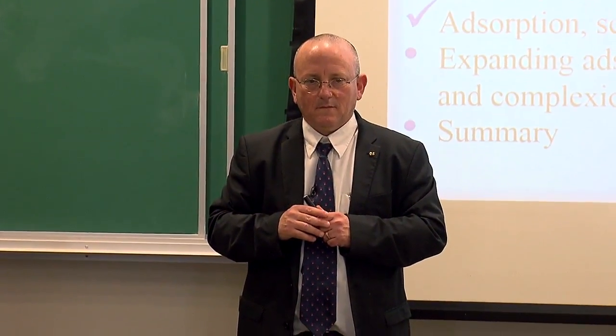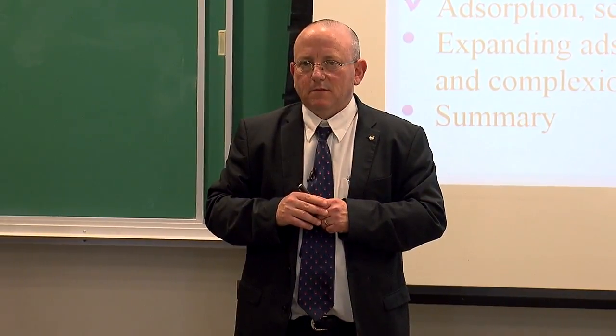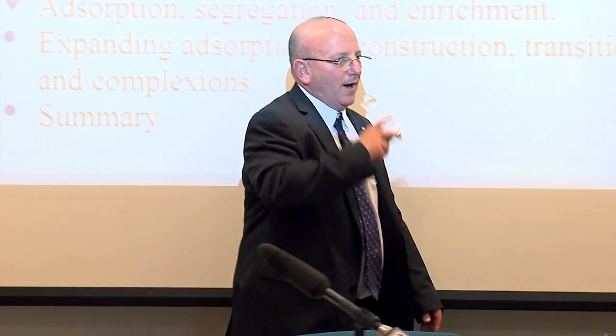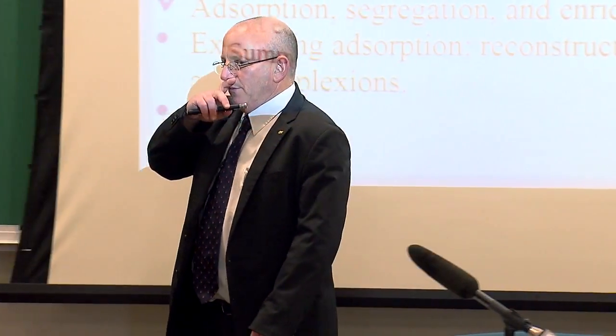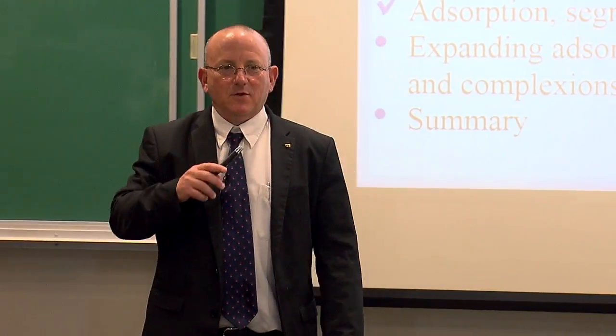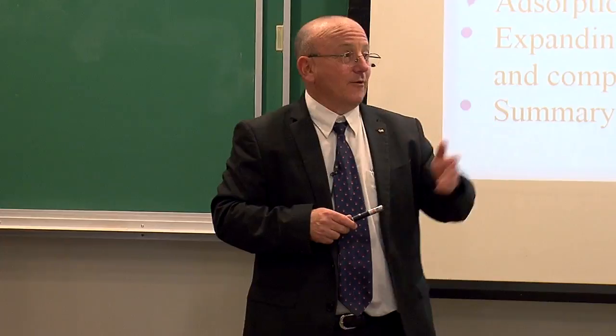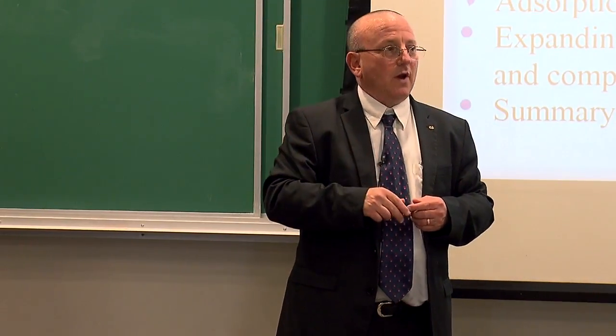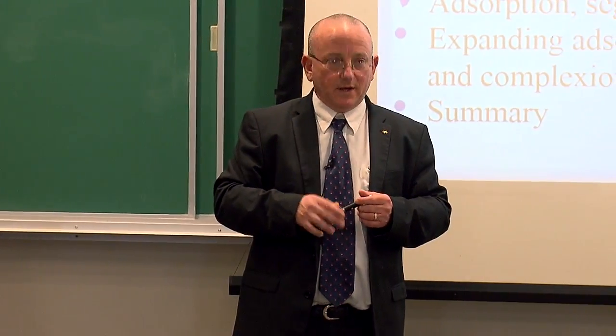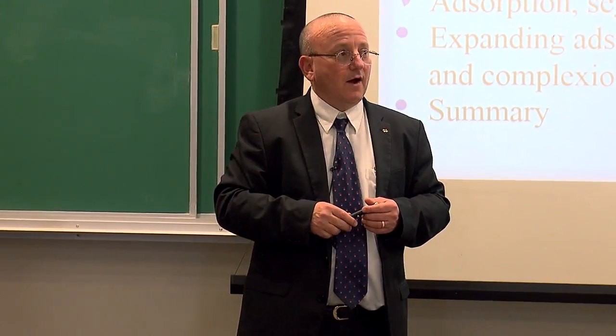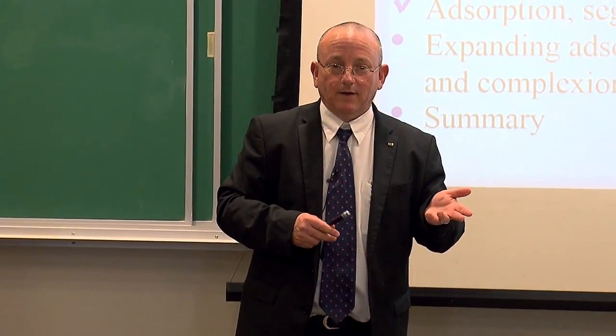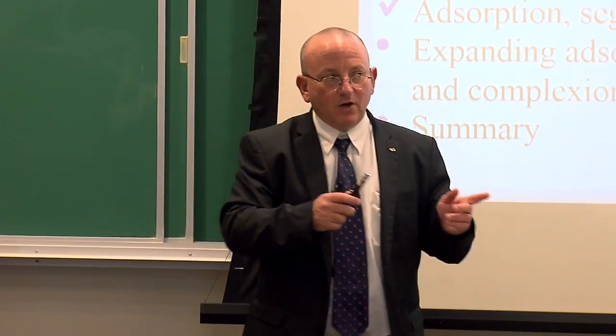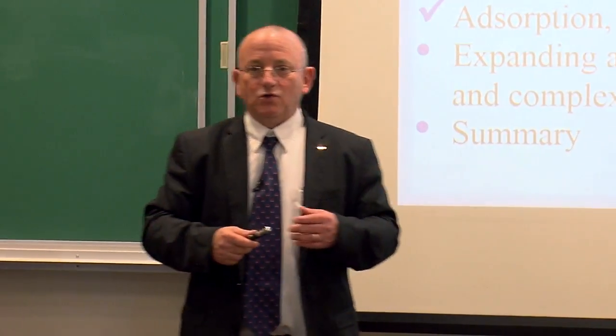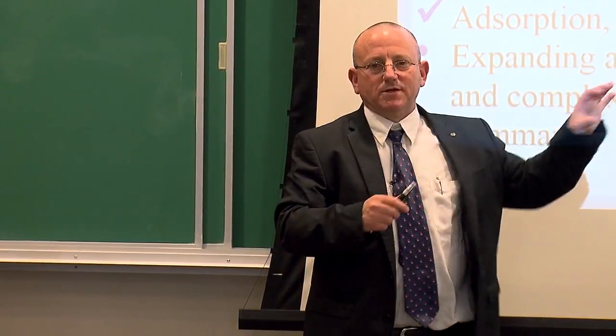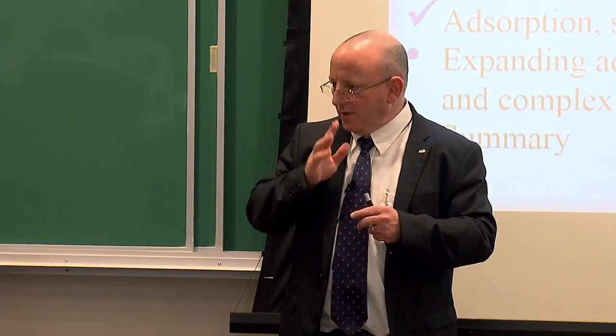But my question is, does this factor into some practical questions of grain boundary engineering or corrosion? Yesterday I was asking questions about some of the growth experiments that you're doing here, whether the thin films that you're putting down are really thin films or adsorbates. That's a question of whether we're in, an adsorbate is a non-wetting condition, and a thin film would then be partial wetting. So that's one example. And then we can go from partial wetting to wetting. Partial wetting would be those droplets that I showed, and continuous wetting along a grain boundary would be a continuous film.